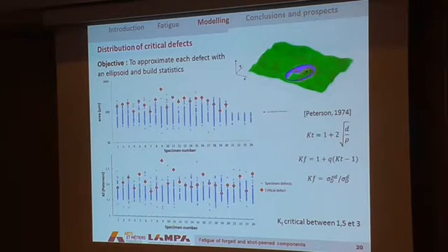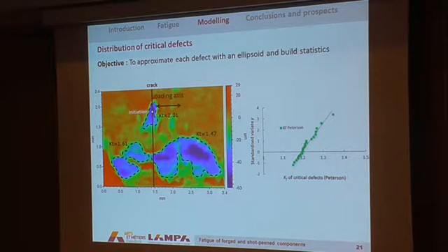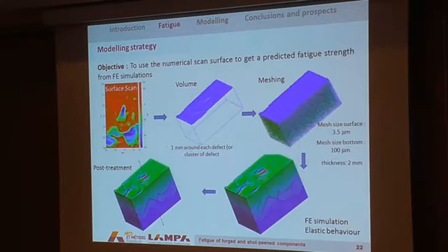What's interesting here with this simple formulation is that when I take this case where you've got a big defect here and a smaller one, the crack initiates in the one where the stress concentration factor is the highest, and not necessarily the largest square root of area. Now, we try to go further by using our surface scan to create a model which represents the real surface with the defect under interest and around 1 millimeter around the defect. We mesh this volume with a mesh size of 3.5 micrometers at the surface and 100 micrometers at the bottom, and we perform some finite element simulation.